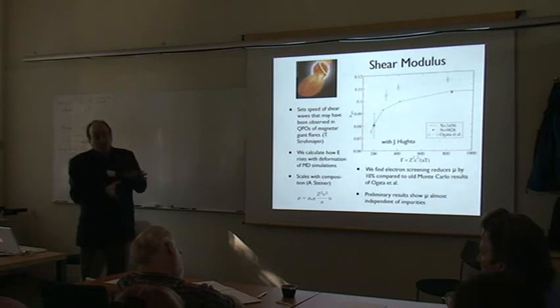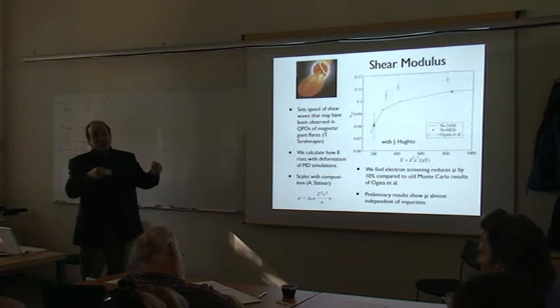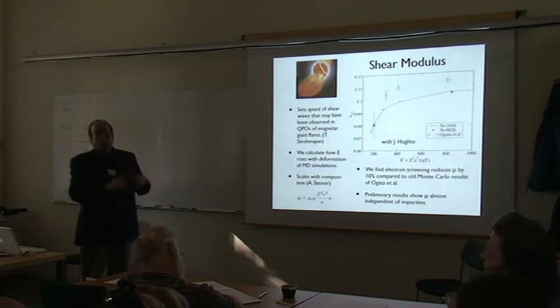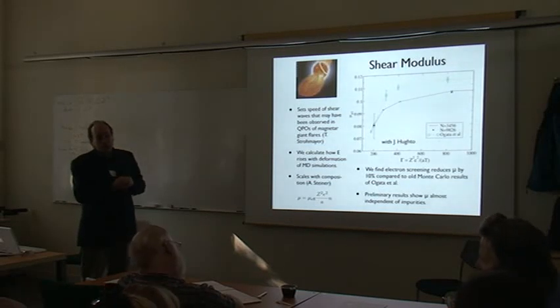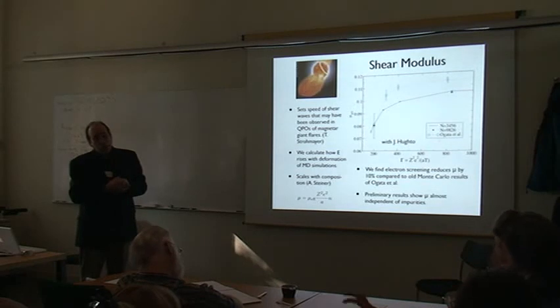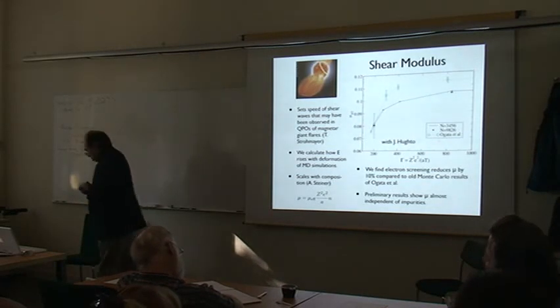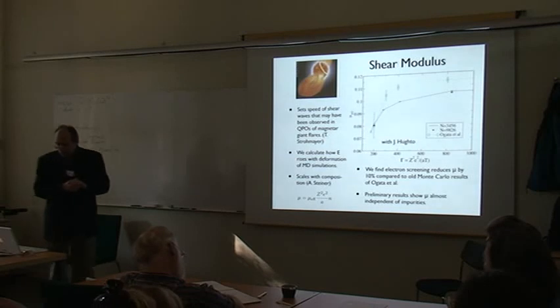And if I had to guess, it will reduce the shear modulus. Instead of just having the point charges deformed and giving you this very strong electric field, the nuclei will deform to try to cancel some of the electric field, so that the internal structure will reduce the shear modulus. Well, I'm wondering if you would lose the catastrophic failure entirely. You just deform through shapes, and maybe it even occurs at somewhat lower densities.